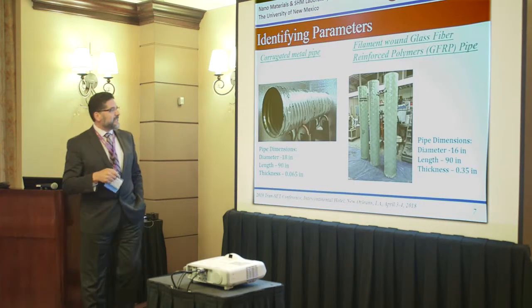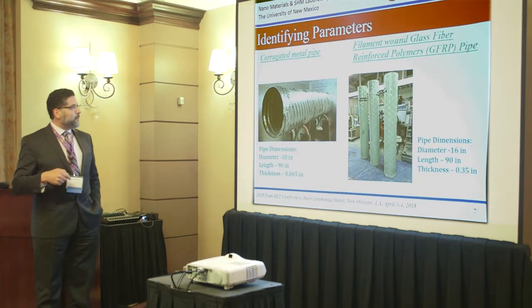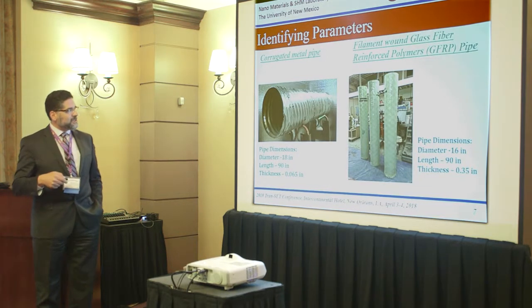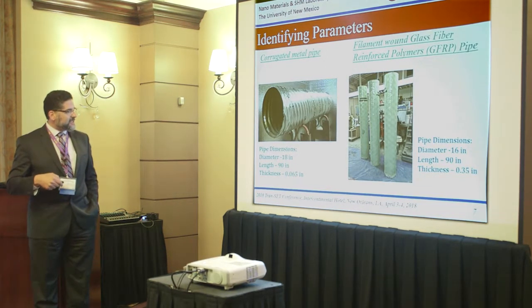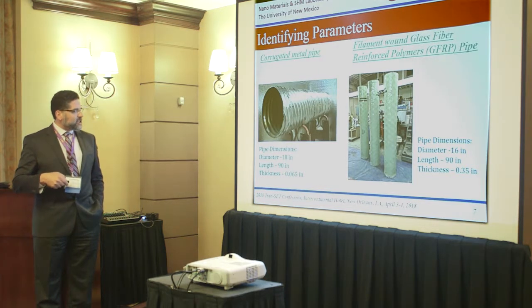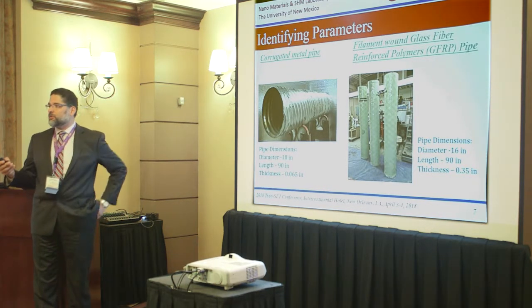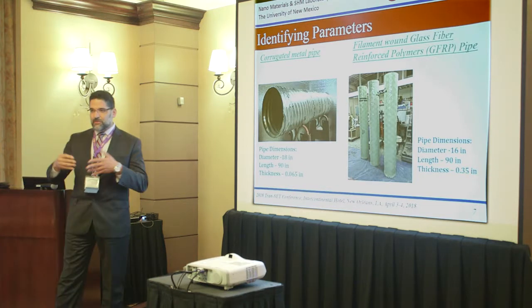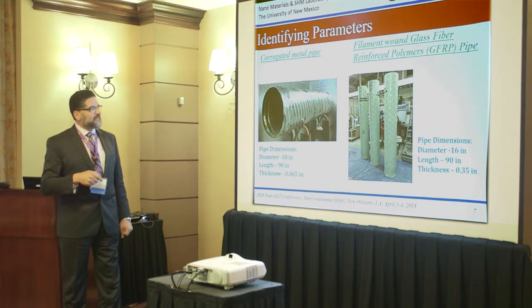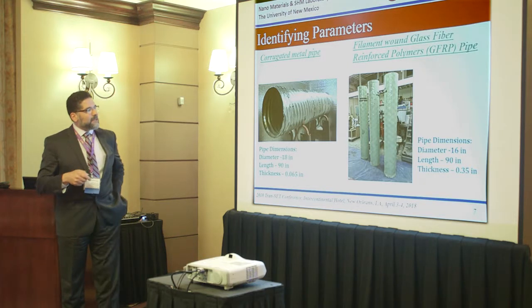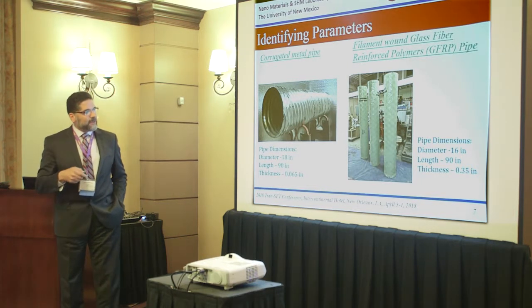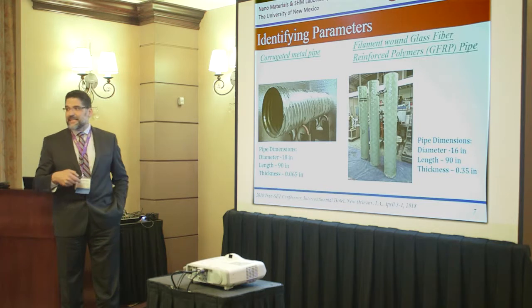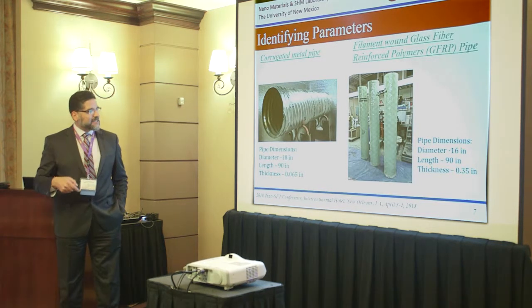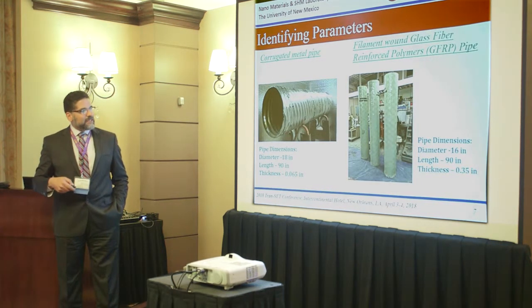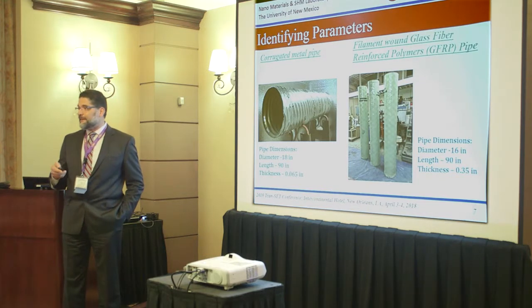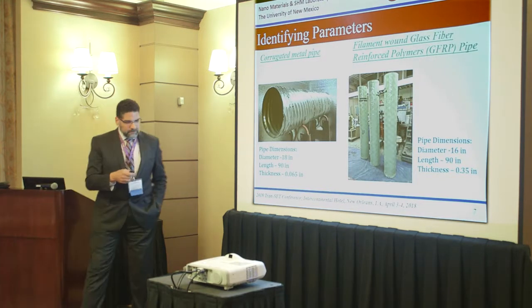So once we identified the design, we went and got a new pipe that has the exact same dimensions as that used in the culvert in New Mexico. That's an 18-inch. We use a 90-inch length of the pipe just because of the limitations we have in testing. Otherwise, we can't do the full-scale testing. We worked with a company in Arizona to actually do the filament winding for us that would fit exactly that dimension and that profile, and that's a 16-inch GFRP with a thickness of 0.35 as per our design to take the load on this.